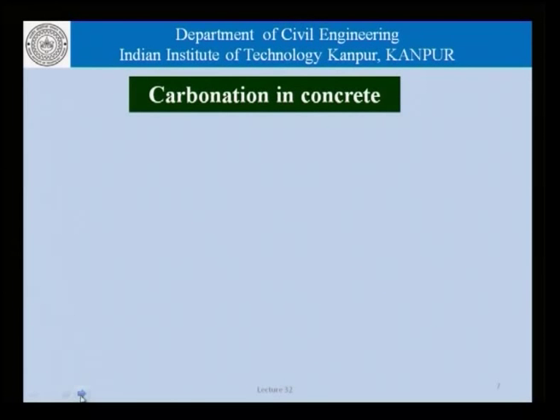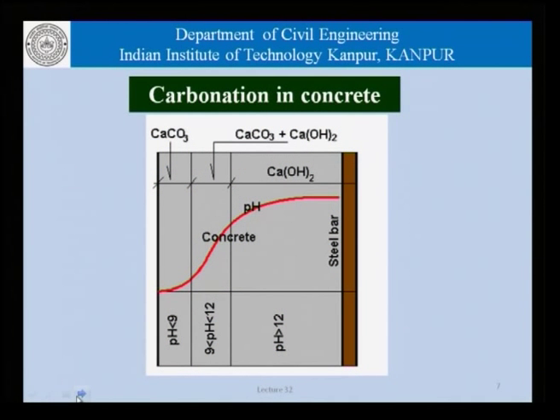Now, once we have that, here is a representation of what really goes on as a result of the carbonation in concrete. So, we have a zone here which is the closest to the atmosphere. So, here is the atmosphere. We have this region here which is the cover concrete, and we have this steel bar here. Now, as carbon dioxide penetrates into the concrete and reacts with the calcium hydroxide within, we can imagine or think that there is this region here where, let us say, a large amount of calcium hydroxide has been converted to calcium carbonates.